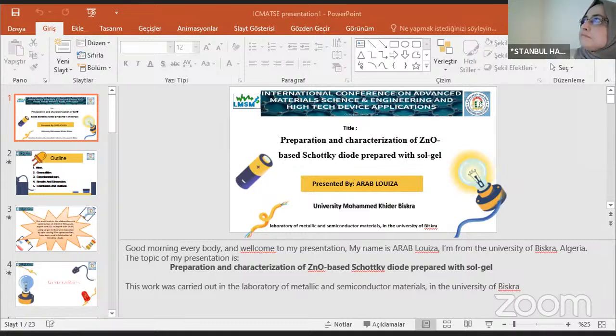So, here we have figures that show the variation of gap energy and Urbach energy for films deposited on Al2O3 substrate and on glass substrate. On Al2O3 substrate, we have recorded a lower value of disorder, the red one, for zinc oxide doped with gallium, which improved the quality of the films. However, for ZnO co-doped with aluminum and indium, we have a higher value of disorder. For the gap, it's logical: we have recorded a high value of gap energy also for zinc oxide doped with gallium. So, the lower value of the gap is recorded for the co-doped with aluminum and indium. This is for the Al2O3 substrate.